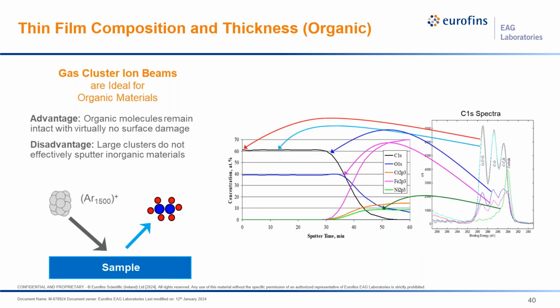So we are now working often with gas cluster ion beams. These GCIBs, which use large clusters of ions to strike the surface, are a lot less destructive and tend to lift off more of the larger chemical species from the sample, leaving less damage on the surface to be tested. So this is just another example where we're actually doing a sputter depth profile of an organic material using XPS and a gas cluster beam. And you can see at various points we can still maintain and have more confidence in the chemistry that we're looking at as a function of sputter depth.